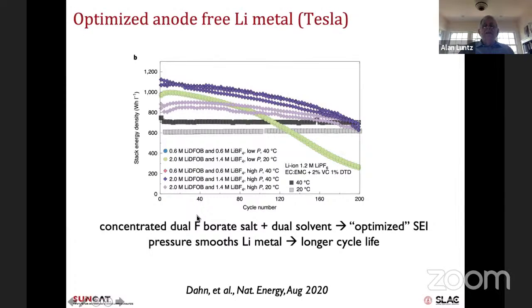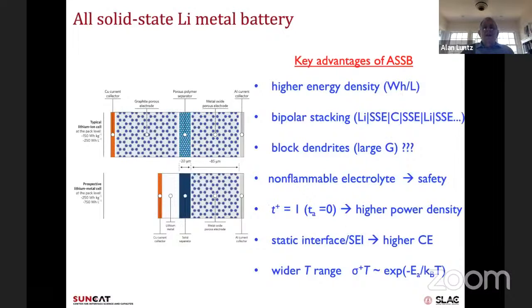But to achieve that, they had to really tailor make the SEI. They used very concentrated solutions, so they didn't have dendrites. They used dual fluorinated salts, they used dual kinds of solvents, and that was how they got the SEI. There's still a lot of games to play in trying to tailor this SEI, I think, so they will continue to optimize it. The other thing they did is they added high pressure, which of course compresses the lithium and tends to smooth it, and that helps to give a longer cycle life because it doesn't get as rough. You can do that in the laboratory very easily. It's not at all clear whether you can do that in a car battery, so I don't know whether that part of it will translate. Okay, now I'd like to go to the all solid. That's all I'm going to say about liquid electrolytes.